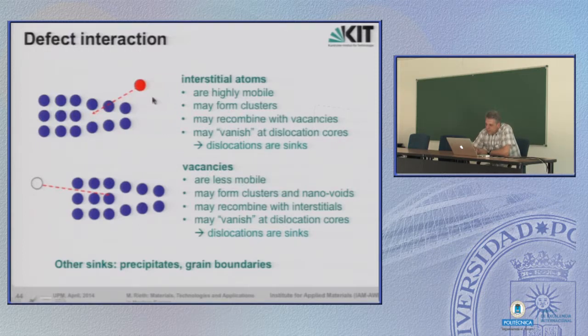If you consider interstitial atoms, and if one moves directly to the dislocation core, then the dislocation has been increased by one additional atom, and the interstitial atom has vanished. The same thing can be thought about vacancies. They are a bit less mobile compared to interstitial atoms, but they also may form clusters and nano voids, or later on even big voids. They may also recombine with interstitials, and they also may vanish at dislocation cores. If a vacancy moves here, then this atom is away and the dislocation has been reduced by an atom.